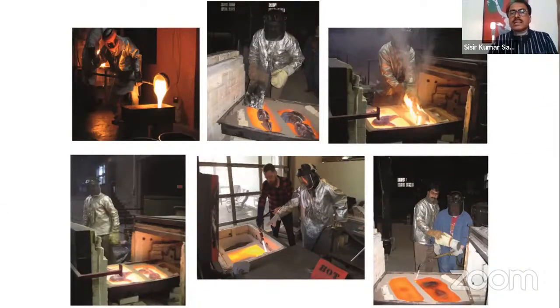You can see this image should be very hot, at least around 600 degrees centigrade, so that it doesn't get cracked when it is kept over the hot, molten glass. So again, here I have placed all the images on the top and covered up with clear glass so that the image goes inside. And again, some bubbles pop up. I clear those bubbles here.